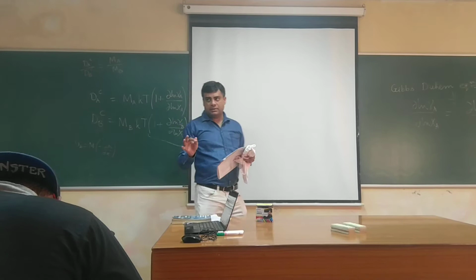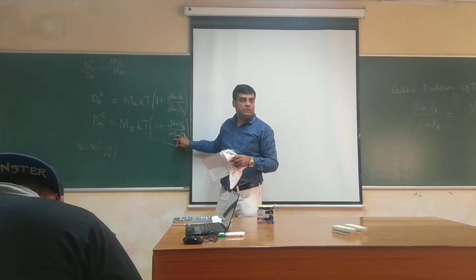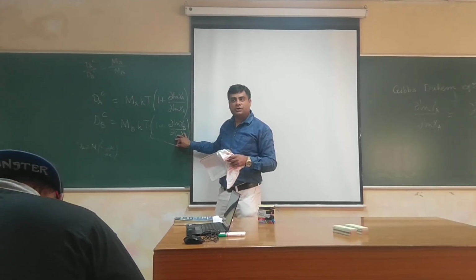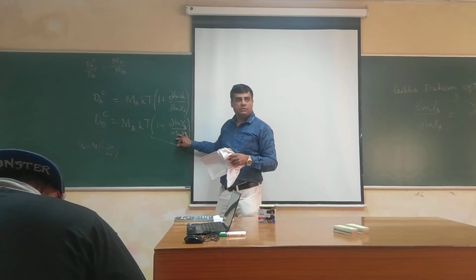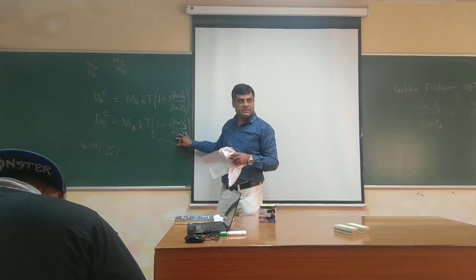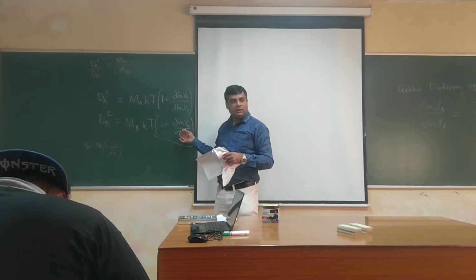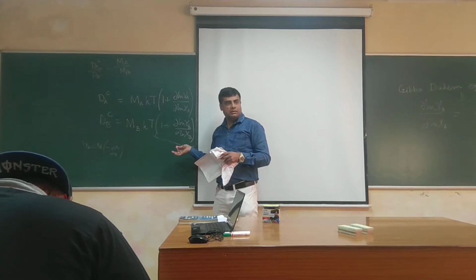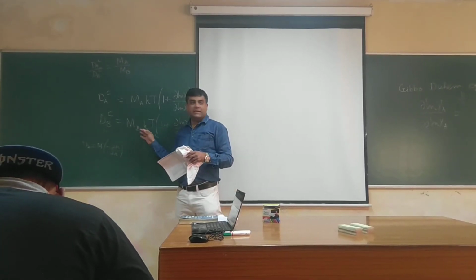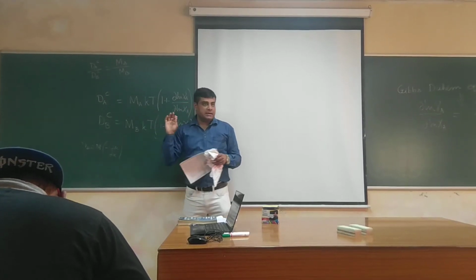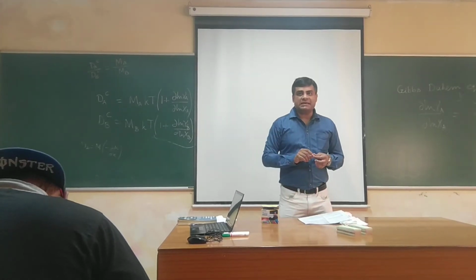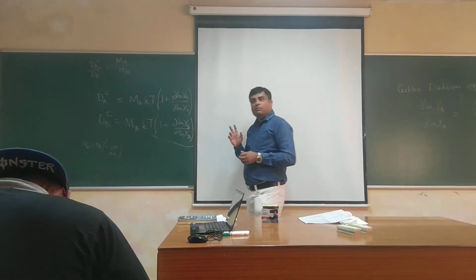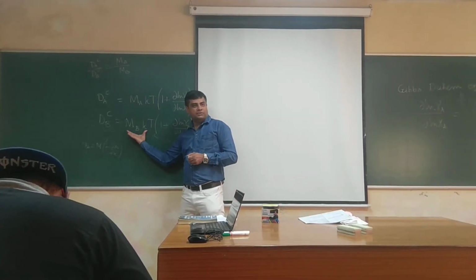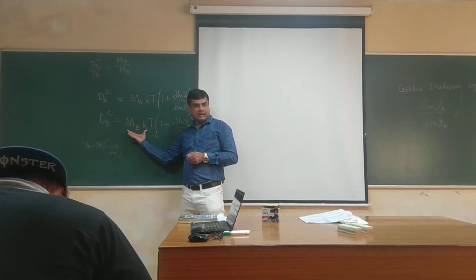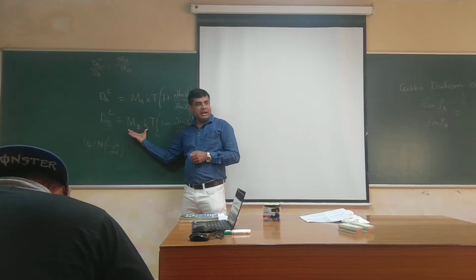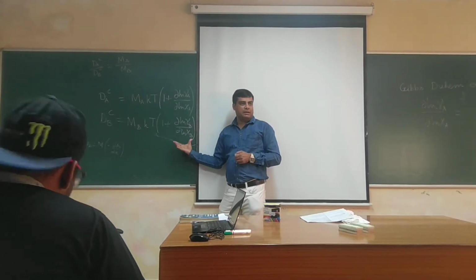And in an ideal solution this becomes 0. Del ln gamma over del ln x, for ideal solution it is 0. Activity coefficient is 1. For ideal solution, this within bracket term becomes 1. So for ideal solution, DB equal to MBkT or DA equal to MAkT. So the intrinsic diffusion coefficient is multiplication of two factors, one coming from the ideal solution in which random jump of atoms happens, multiplied by the non-ideality given by this thermodynamic factor,